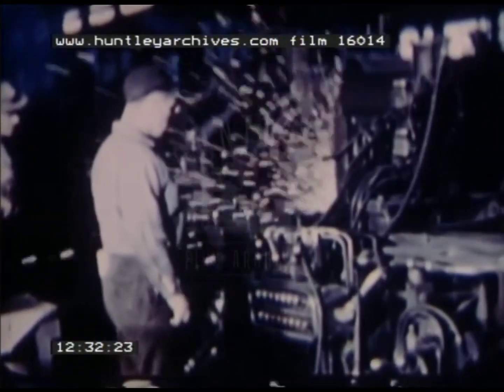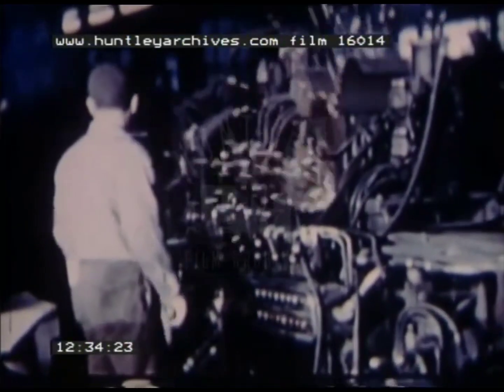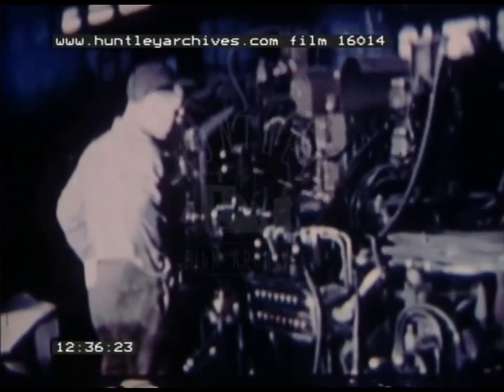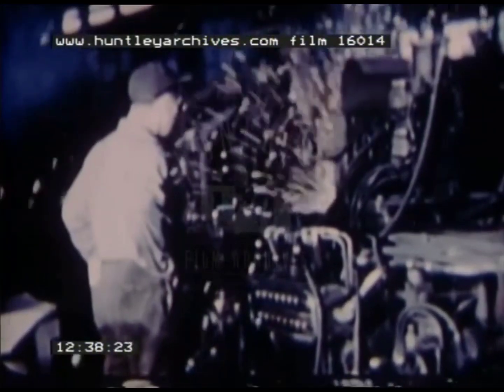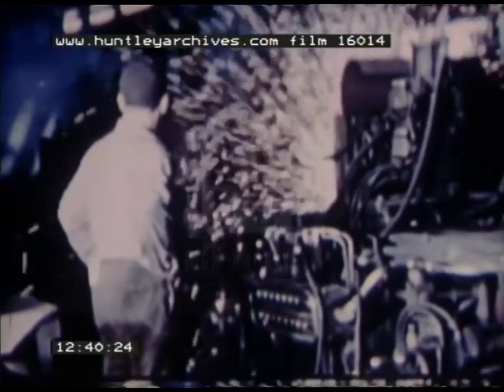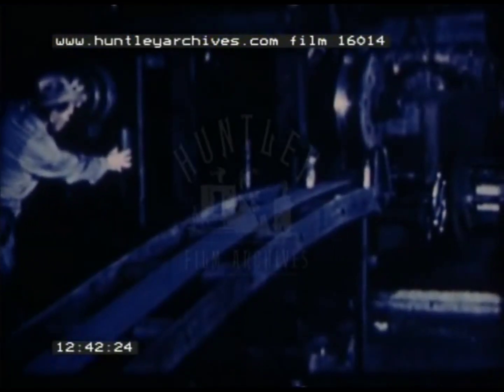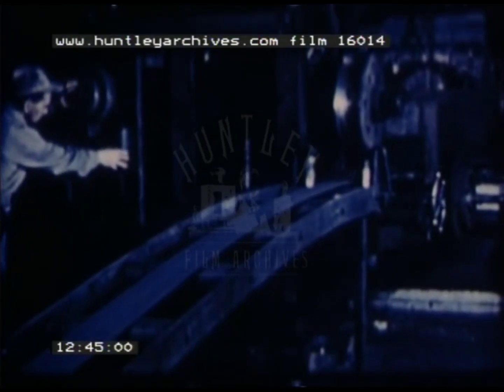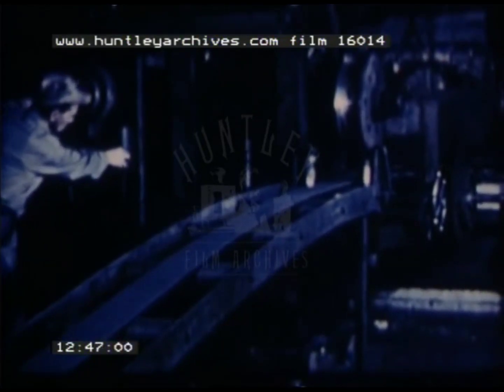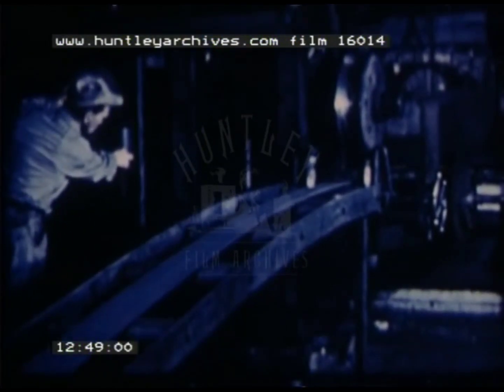At the continuous weld pipe mill, where pipe from 1/2 to 4 inches is made, the skelp is uncoiled and fed into a machine that electrically welds the ends of each coil together, so that the skelp can be fed continuously into the pipe-making machine. This continuous ribbon of steel is first fed through a long furnace, where it is heated to more than 2,000 degrees, and the edges are raised nearly to the melting point. Emerging from the furnace, the steel passes through a set of forming rolls that bend it into circular pipe and press the near molten edges together.